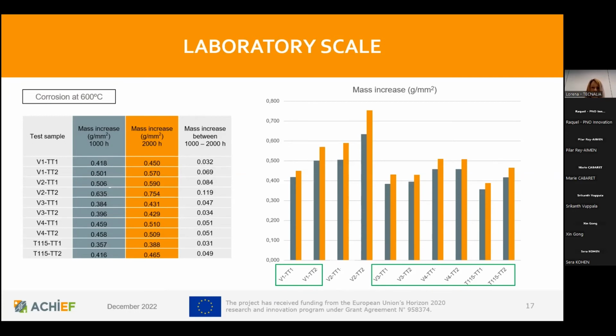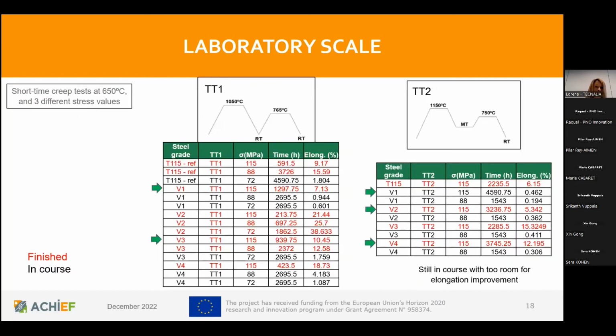For the moment, the study says that the mass increase observed for all cases can tell us that we are seeing a similar behavior for all the samples, but with the exception of the sample V2 for thermal treatment 1 and thermal treatment 2. But the rest of the samples behave more or less similar to the reference steel, at least in terms of mass increase. The creep tests carried out at 3 different stress values can be divided into 3 types of tests.